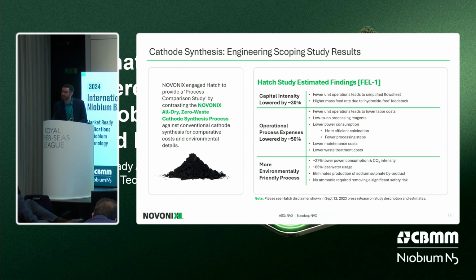And the results are summarized in the table on the right-hand side. Really, the CapEx intensity decreases by roughly 30% going all dry, and that's owing to fewer unit operations and having a higher calcination efficiency. You're dealing with metal oxides that don't shrink during calcination, unlike metal sulfates, which turn into a metal hydroxide, which is a lot of water being carried around. So your calcination efficiency ends up being higher.